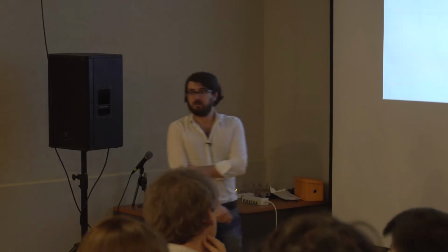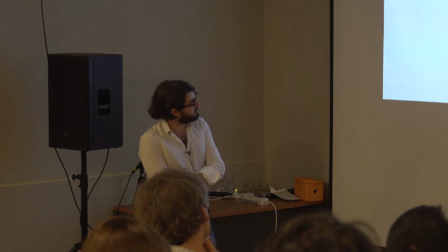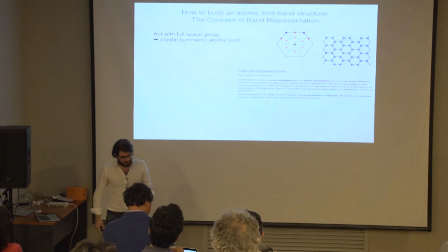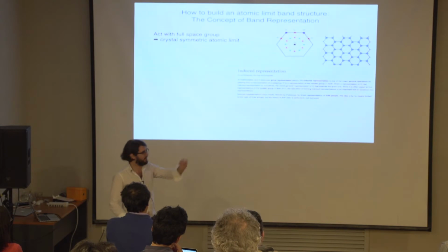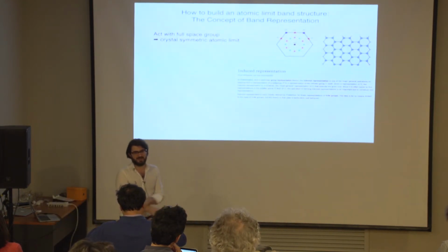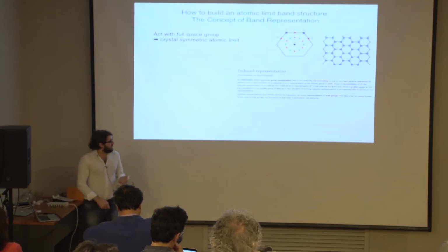What is the importance of the Wyckoff position if you don't have any atom? Yeah, so if I don't have any atom there, but somehow my band is a representation of that position, then it means that my center of charge has moved to that position. And that means there's actually a transition between the center of charge being here and the center of charge being here. So it means that I have to close the gap, and that's a hybridization transition. That's the meaning. Hybridization is just moving from one center to another. Okay, good, thank you, yes.